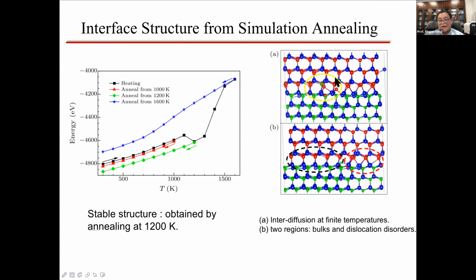cadmium telluride space. Generally, the structure is a perfect structure with positions and dislocations, like edge dislocations, so it can be imagined. This structure is right. So in this way, we get the structure model for these systems with these AI potentials. As soon as we get these structures, one can really work on other properties, to calculate or simulate why this buffer is necessary. So this is a way to solve the problems of real devices.